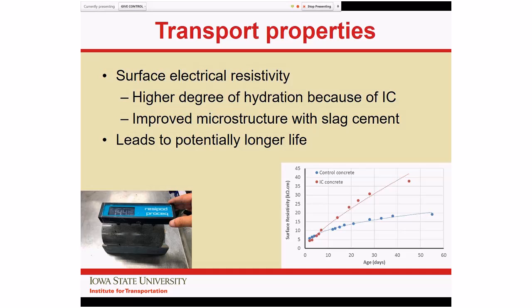Okay, here's a photo of the resistivity device. It's basically just a little 4-pin probe. You hold it on the side of a wet cylinder and push a button, and it spits out a number which is in kiloohm centimeters. And again, the joy of this test is that you can test the same sample. It's non-destructive. So having done the test, you can put the sample back in under curing, come back a few days later, and do it again.